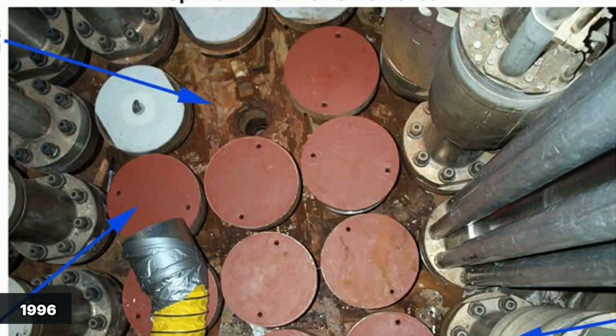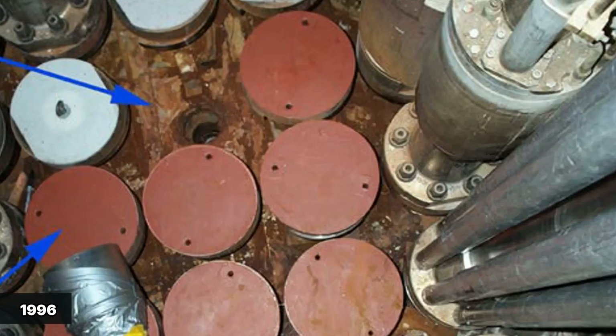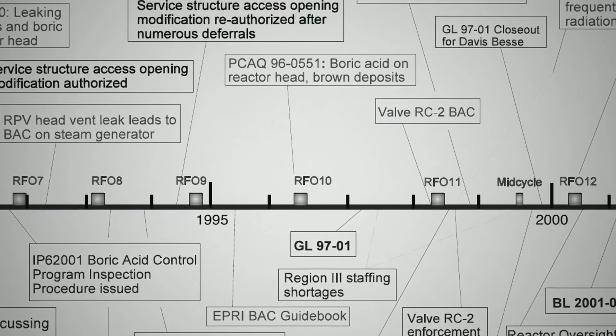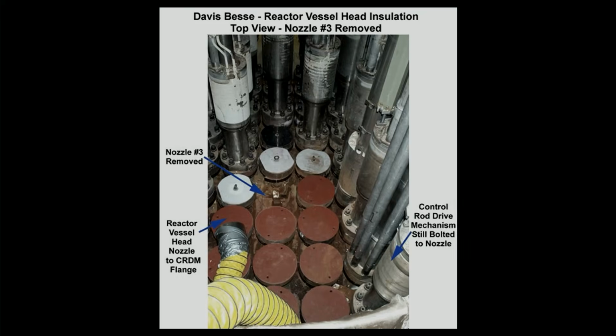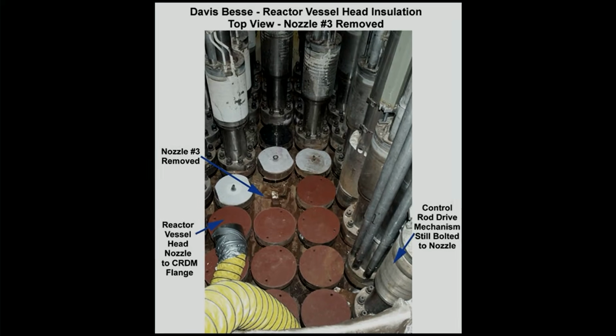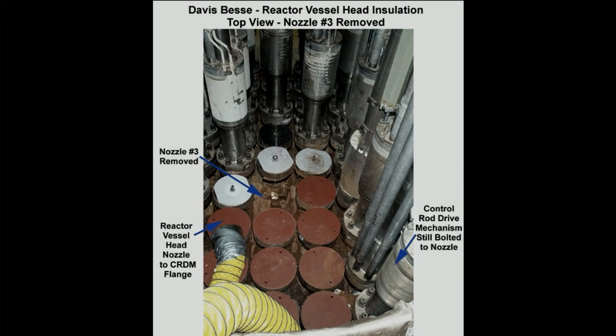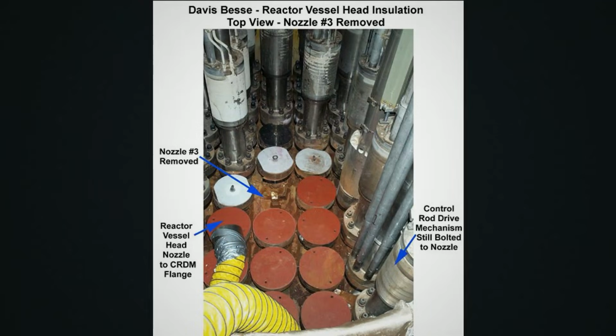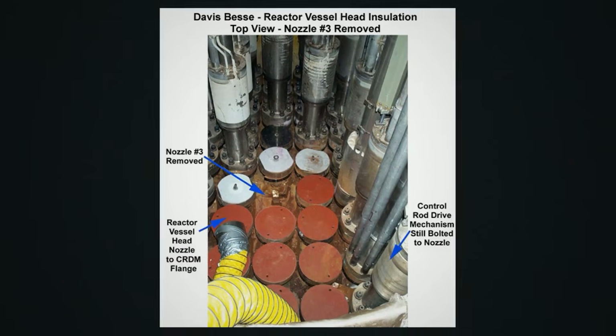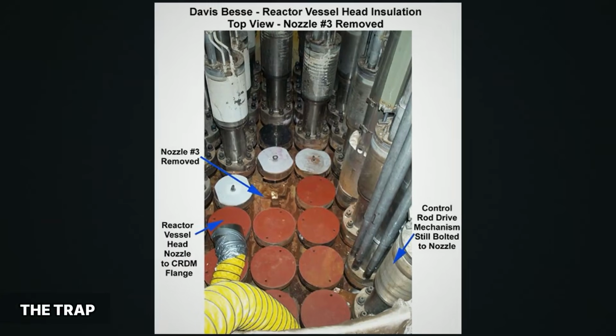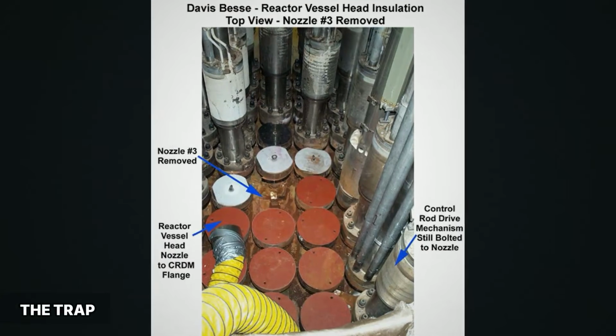Now the record. In 1996, boric acid deposits are documented on top of the Davis-Besse head. That is the first entry in a paper trail that runs for 6 years. The deposits matter for 2 reasons. One, boric acid on the outside of the lid means borated water got to the outside of the lid, and the only way out is through a crack. Two, and this is the part that turns a problem into a trap, the deposits themselves block the view. Once the head is crusted, visual inspection for leakage stops working. The evidence of the leak becomes the thing that hides the leak.